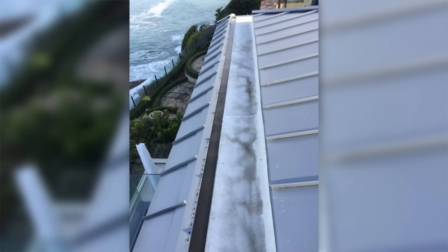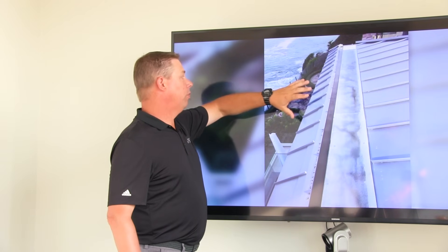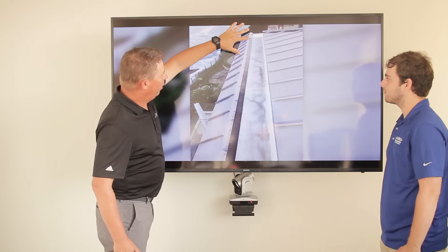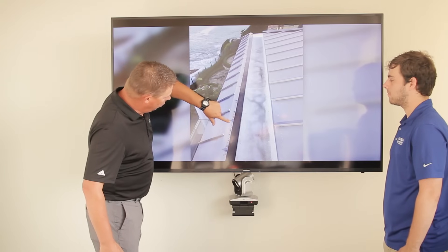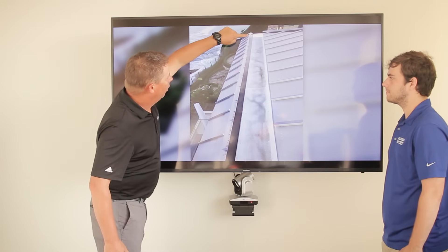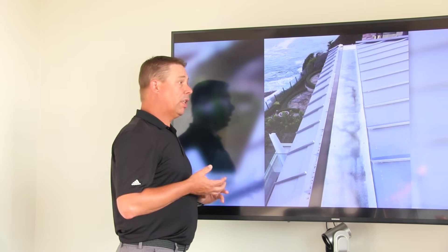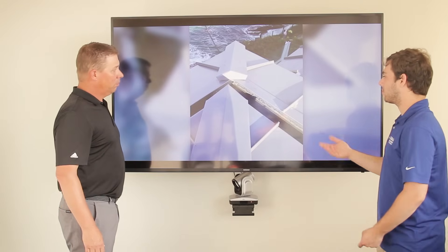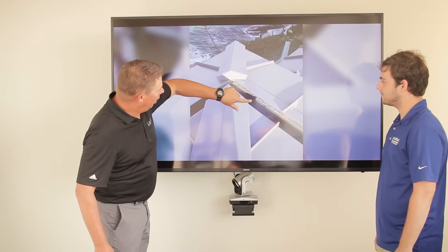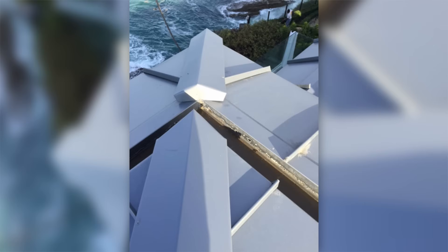For this example, we have a pre-finished metal roof that has copper gutters. The problem here is that the copper gutters — water gets in there and the splash is actually creating corrosion throughout this entire lineal design, and that material is failing. Water splash and runoff from a copper pipe can all lead to dissimilar metal corrosion. Here's a closer shot of the copper gutter — you're seeing dissimilar metal corrosion throughout this entire line of pre-finished material. You can actually see where it's completely gone — it's just dissolved.